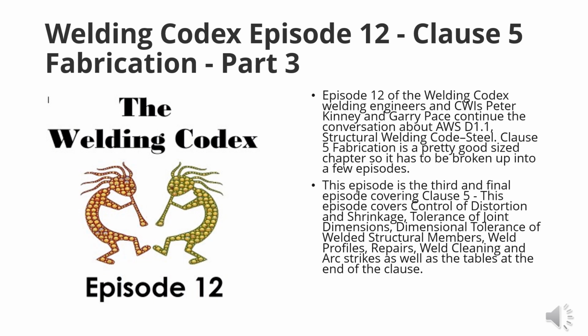So you know that if you had any crater cracking or any kind of crud in either the start or the finish of the weld, you've got it outside of your weld. So a lot of times you'll have porosity with 70-18, on the start. It might not be a significant amount of porosity, but sometimes you'll just get a little bit of porosity on that start and let's say a crater crack on the end. So a lot of times a weld tab is convenient for that.